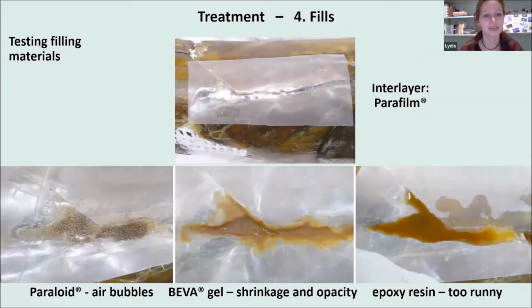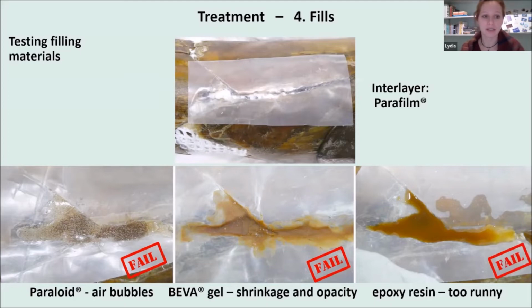I tested various materials to achieve the desired fill. My first choice, the acrylic adhesive Paraloid B72, didn't work for me, as it was very time consuming to cure sheets without creating air bubbles and to mold the sheets into position. My tests with Beva gel also failed, mainly due to the high shrinkage. Epoxy resins achieved the desired colors and opaqueness, but were too runny to apply on curved surfaces. I considered molding and casting the missing areas, but again, I didn't have enough time to develop a successful system.